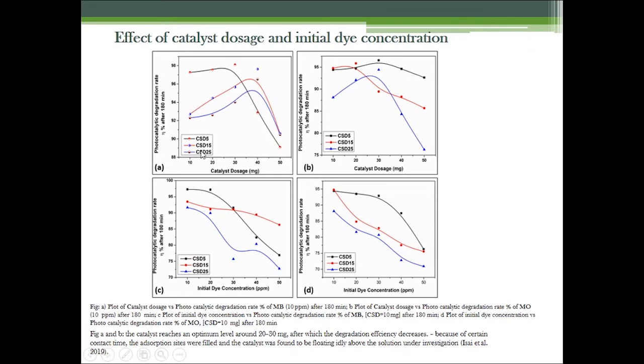So the effect of initial dye concentration on the dye degradation rate percentage was studied from the range of 10 to 50 ppm aqueous solution of both methyl orange and methylene blue. The huge amount of dye gets absorbed on the active sites, thus blocking the contact between the radicals generated from the conduction and valence band of copper oxide nanoparticles on the irradiation of the light source.